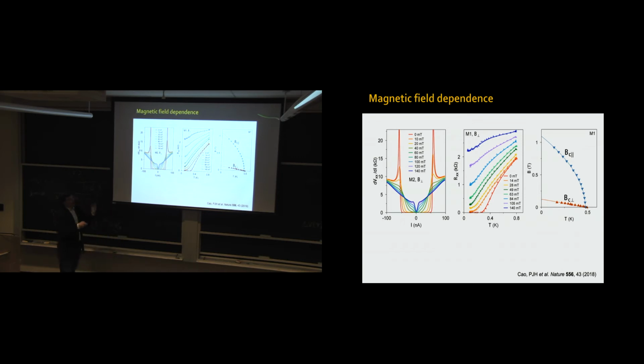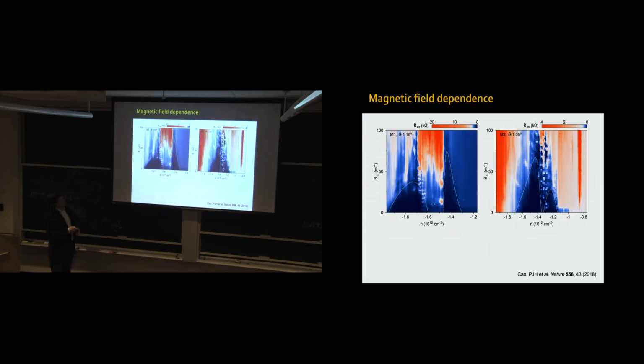In fact, you can do all of this again continuously because you have your density knob. So these are resistance versus density and versus perpendicular magnetic field—you have the superconducting domes, but now in magnetic field rather than temperature. But when my students showed me this data, I said, it's not as pretty as the previous data, with these temperature numbers.